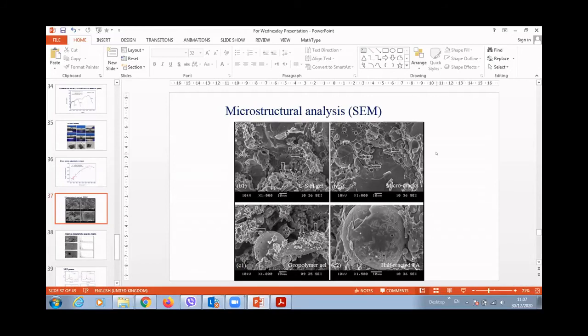The other investigation is microstructure analysis. We took samples from the paste, exposed them to SEM analysis, and studied which kind of gel or bonding exists. We found, as the other presentation shows, there is always the formation of C-A-S-H gel or N-A-S-H gel, and some of the samples show non-reactive or half-reactive fly ash, which appears in spherical form. This is because the time is not enough to react, and it has a relationship with the quantity or ratio of alkali activator you used. So the reaction goes slowly.